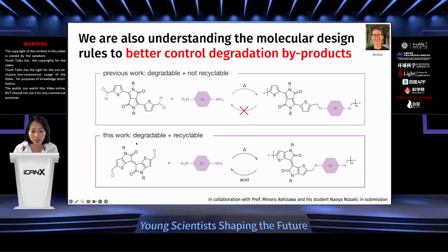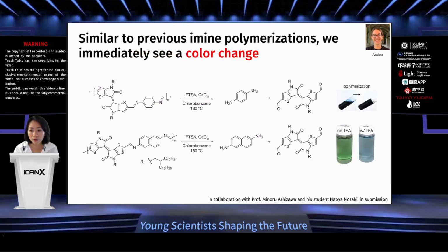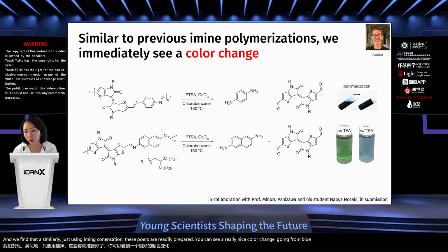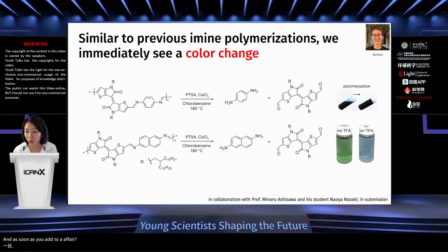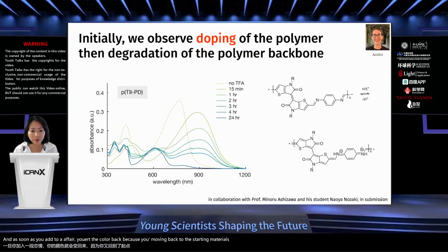So we devised a new TII compound where now we have the dialdehyde also on this compound and a diamine. However, we have a different system where we hope that ring opening wouldn't happen. We find that similarly, just using imine condensation, these polymers are readily prepared. You can see a really nice color change going from blue to green. And as soon as you add TFA, you revert the color back because you're moving back to the starting materials.